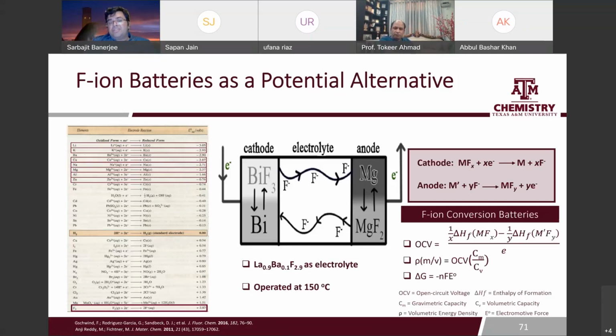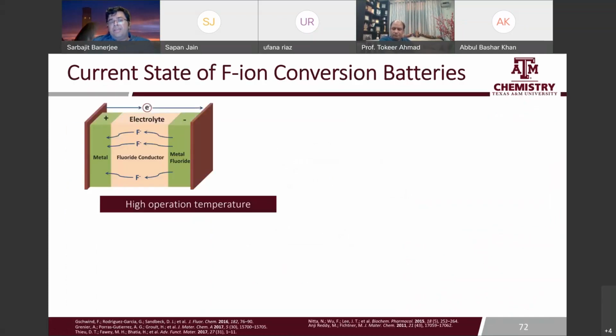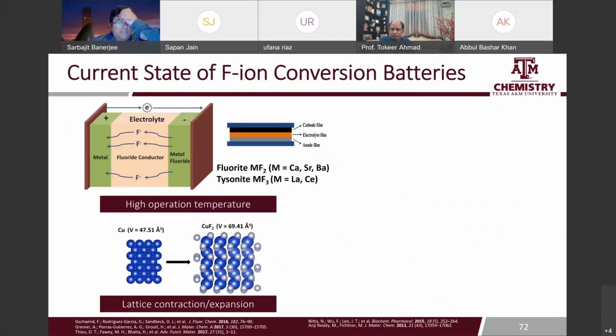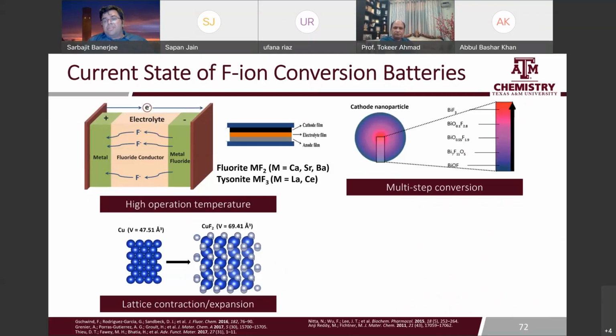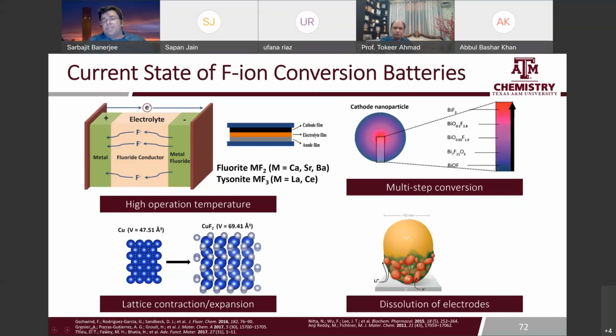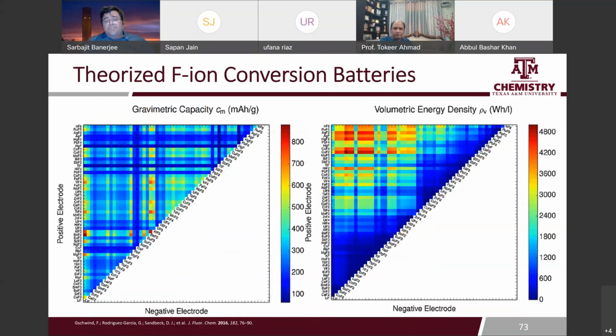It has, again, its challenges. The operating temperature is quite high. These are typically solid-state electrolyte cells. Because these are conversion electrodes, you're converting a metal into a fluoride, there's a very large volume change that reduces cyclability. There are typically multi-step conversions involved, and then the electrodes will often dissolve into the electrolyte, so they're unstable. So again, the challenges with the passivating film. These are all major problems. Again, the promised gravimetric capacities for these conversion electrodes can be quite high. These are some predictions. Depending on the pair you pick, you can get good conversion.